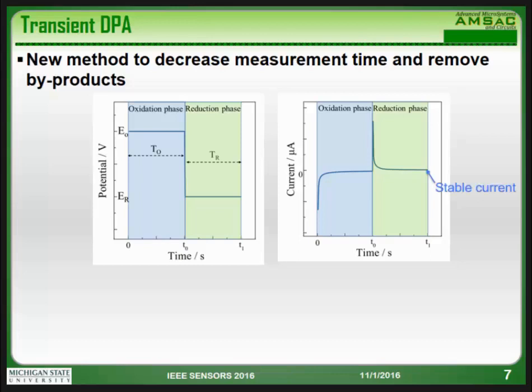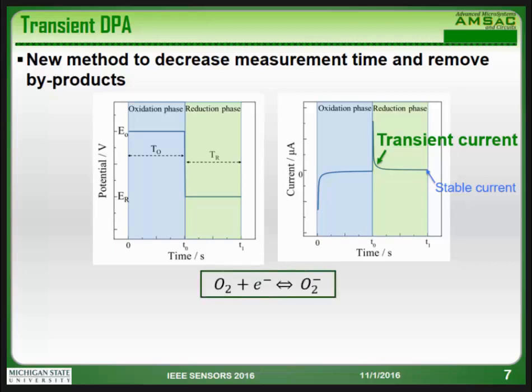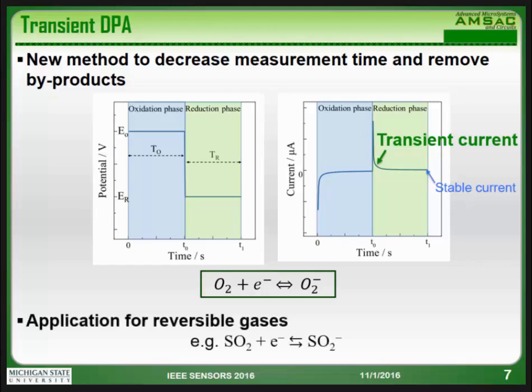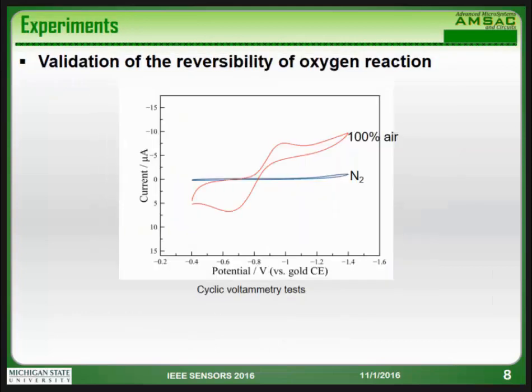The double potential method generally uses a very stable current here. So we are thinking, is it possible to use a transient current, which is set here? Before the current is stabilized, it is possible for us to use it. Based on the reversible reaction, we are trying to use oxygen to validate our method. And what we want to mention is that this method is also possible for other reversible gases.